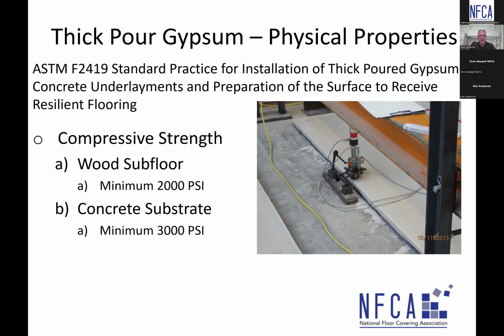Ironically, the gypsum standard, which is also built by the same F06 committee, F2419. So the gyp over concrete, in that standard, it details a 3,000 psi, and in that standard, the gypsum compression strength over a wooden subfloor is detailed at 2,000 psi. But F710, the standard for preparing concrete to receive resilient flooring, also says 3,000 psi.